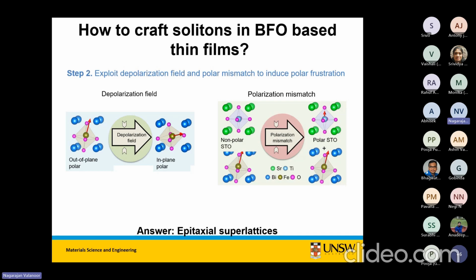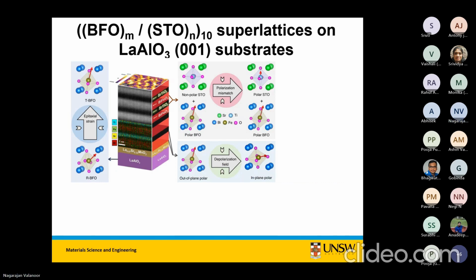So do something like the other guys did, PTO, STO, just do an epitaxial superlattice, but make sure that you never relax the BFO layer to form mixed phases, which means we can do this experiment only in that chamber with the long throw. Any standard PLD chamber, I think, is not going to give you these structures that easily. I may be wrong, and I'm happy to be proved wrong, but I believe the reason we solved this compared to others is because we got this chamber with the long throw.